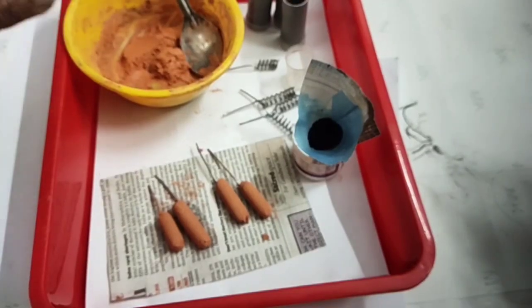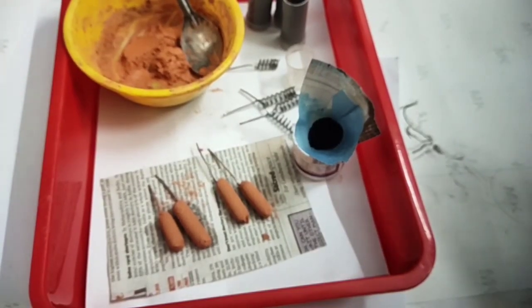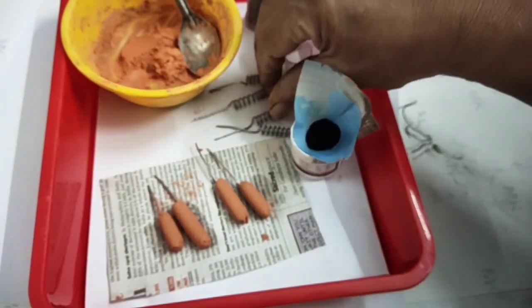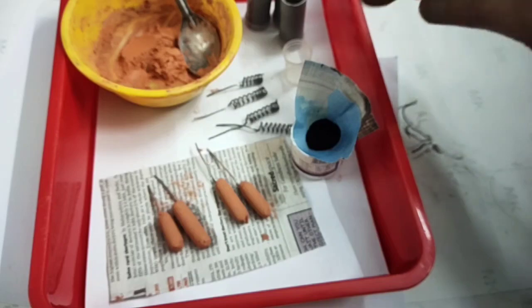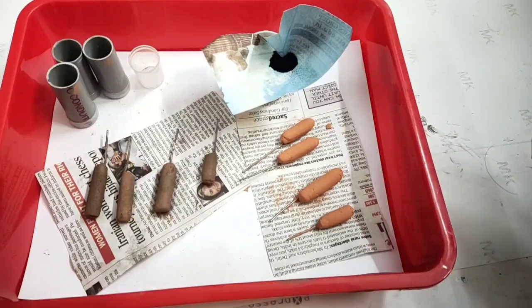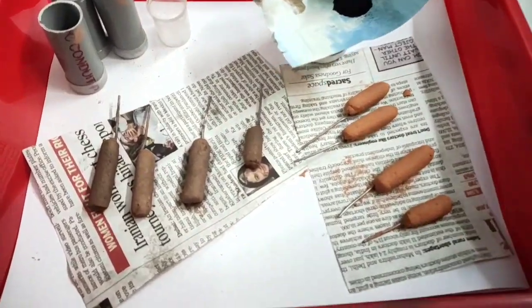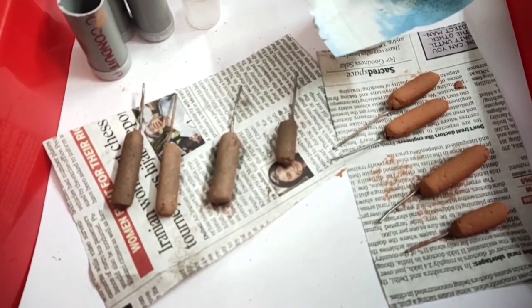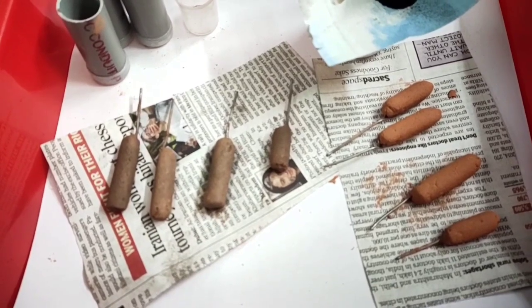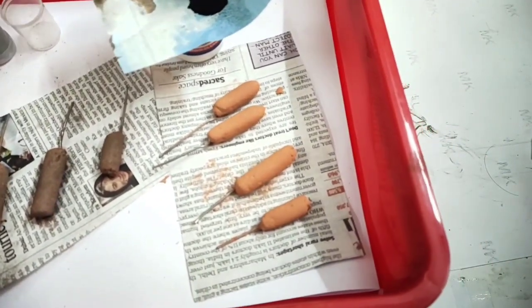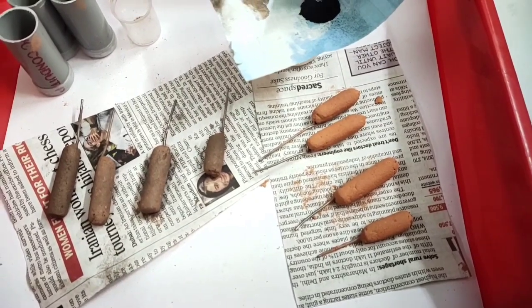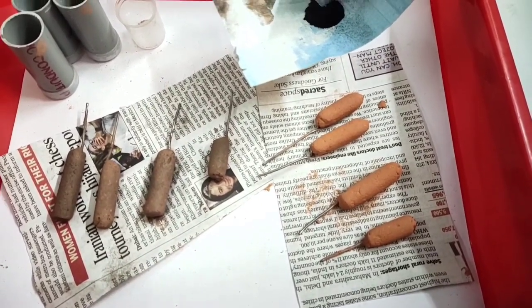Now I'll add carbon, make a smooth paste, then coat like this to the remaining electrodes, these grids. Now we have prepared the negative electrodes, so it is with the added carbon, that is the difference. These are all positive electrodes, but both are called as green electrodes.